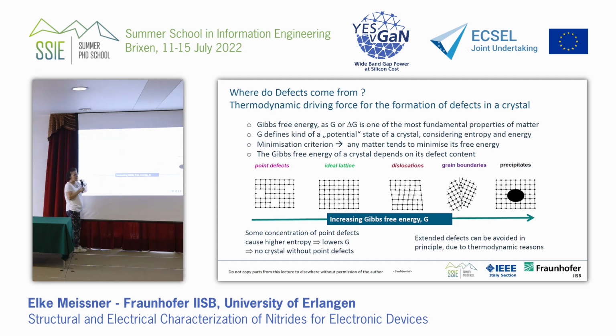So you put in some defects like vacancies or interstitials, which creates a lower energy. By this definition, there will always be some concentration of point defects in a crystal lattice. The perfect lattice will consume more energy. So from this point of view, it lowers the energy to put some point defects into the crystal, which means that fundamentally there will be no crystal with no point defects. You can get as close as possible and remove them as much as possible, but from an energetical point of view it's really hard to achieve.